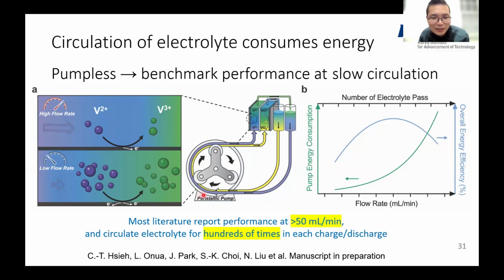But people usually in the literature use very high flow rate, more than 50 milliliter per minute. And they circulate the electrolyte for hundreds of times in each charge or discharge. And because in these papers, they don't care about the pump energy consumption, which is important for practical application. So we actually focus on this and the benchmark, and then try to figure out what's the minimum number of passes you need to make this flow battery still work.